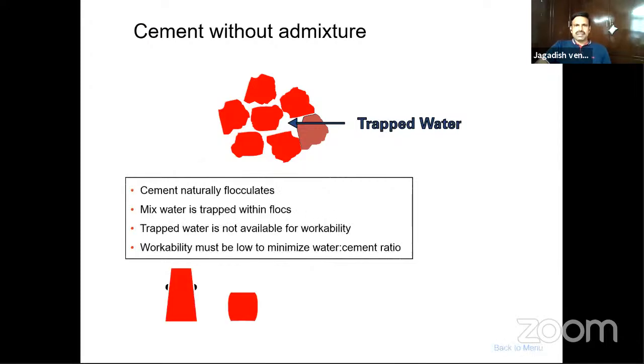The basic reaction of the chemical admixture, that is plasticizer: when water is added to the cement, it naturally flocculates. So the mixed water gets trapped inside these flocs. To release the trapped water within these flocs, we add plasticizer or the chemical admixture, such that the trapped water gets released and the workability is increased without adding more water.